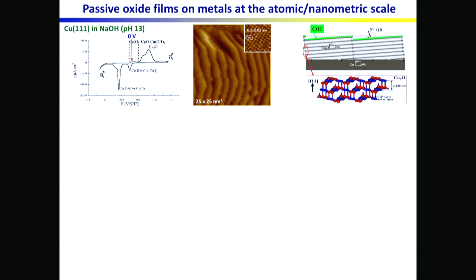But this direction of growth is stabilized by the adsorption of OH at the surface. So the key factors there are, one, that the passive oxide is crystalline, which was a new finding at the time we did these measurements, because most people saw that passive oxide films were amorphous, and they were basing that on just measurements done on silicon dioxide at that time, because these films are very thin.